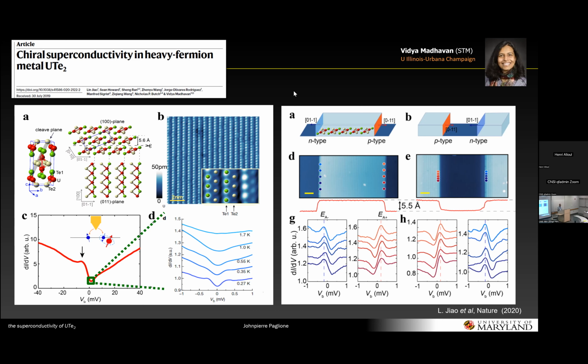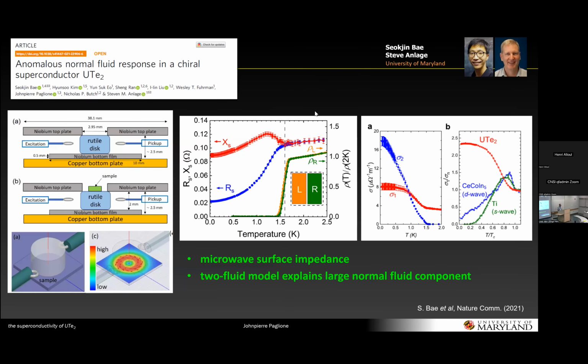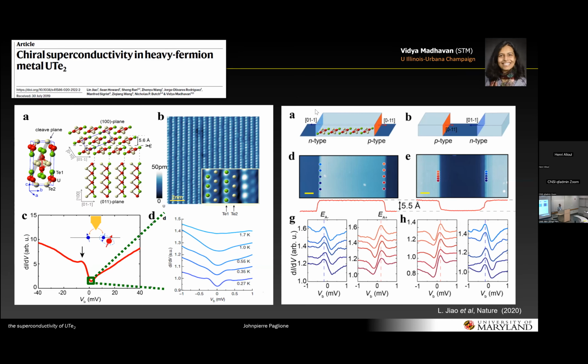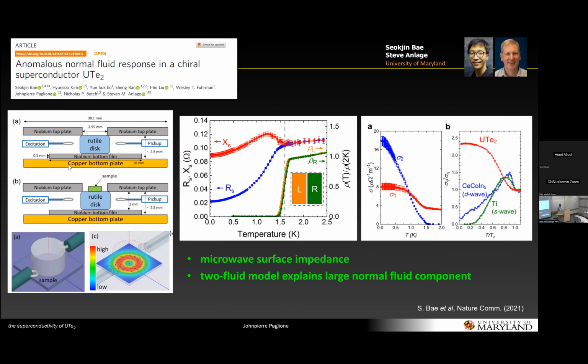And that hasn't gone away in the salt flux grown samples? That has not gone away. That's correct. Has it been measured in the salt flux grown? Yeah, apparently. Yes. And to add further, the same experiment that was done to measure penetration depth, which is a microwave impedance experiment, also sees a very large residual conductivity that is associated with the surface, because we know the bulk does not have any conducting quasiparticles at these temperatures.